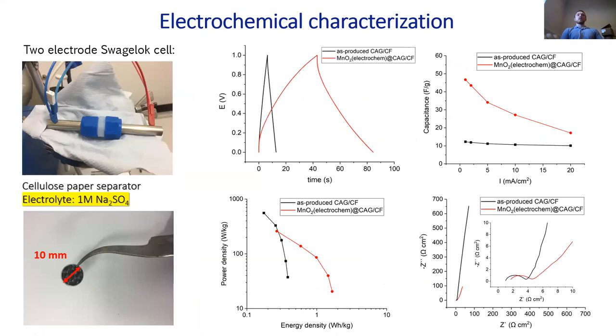To better understand the behavior of the full cell device, we use the specialised cell similar to the one used by Servann. But in this case, we have two symmetric electrodes, and this type of test, galvanostatic charge discharge, actually simulates the behavior of conventional supercapacitors, so it can be directly compared.